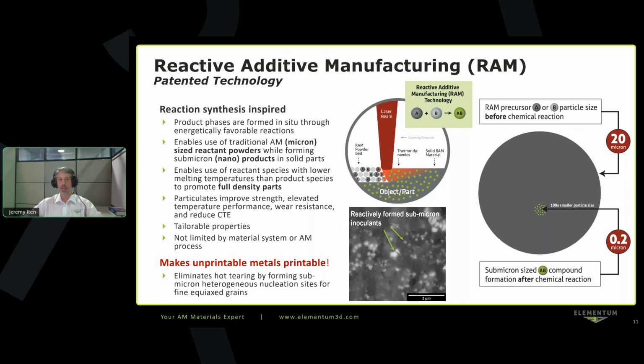Many materials at the nano size will rapidly pick up moisture or oxygen from the environment, for example. They can potentially get airborne, things like that. So we do not work with nano powders for these RAM materials. We're able to work with traditional micron scale feedstocks. This also allows you to use reactant species with lower melting temperatures than the product species to promote full density parts. If you try and just put high melting temperature ceramic phases into your feedstock powders, you may have trouble with fully melting those, getting bonding and wetting between the alloy system. So that can be very challenging. Also, the very high surface areas can lead to gas inclusions and so on.